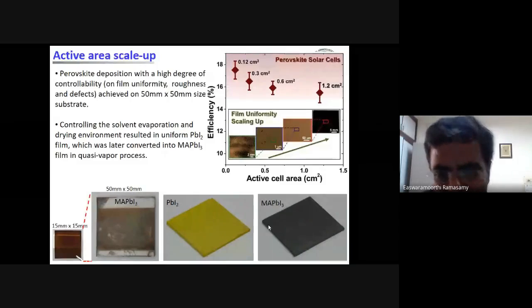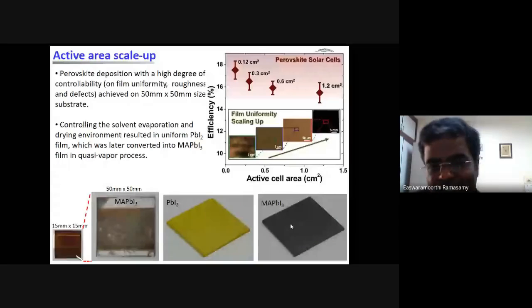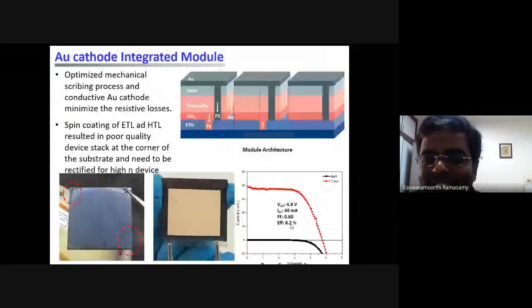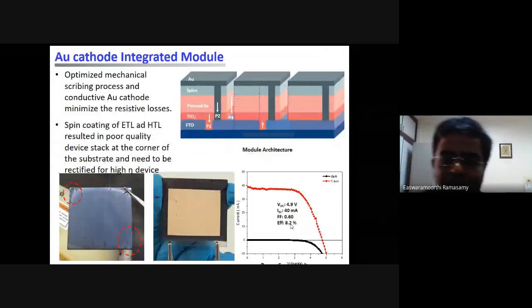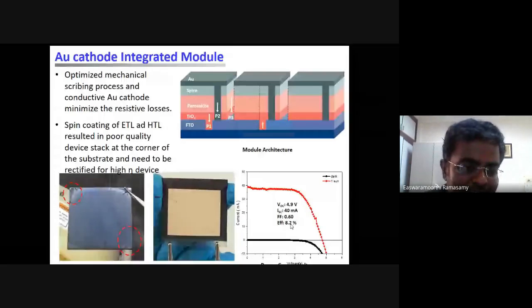The 50 mm, this is 50 by 50, and processing of the perovskite ink. We moved from the one-step to the two-step sequential deposition approach. Here, first PbI2 is formed and then it is converted into MAPbI3. So the uniformity of the perovskite absorber was greatly improved, and therefore we were able to get a higher efficiency device. So this is the strategy behind the upscaling of perovskite solar cells from laboratory to prototype module.